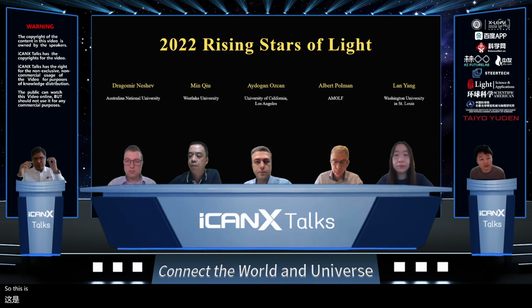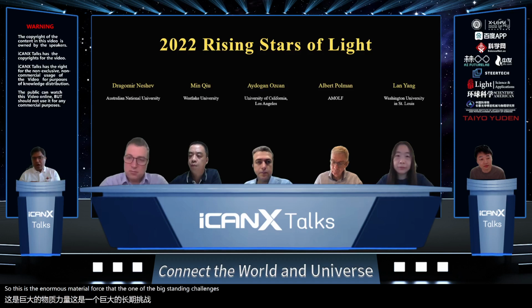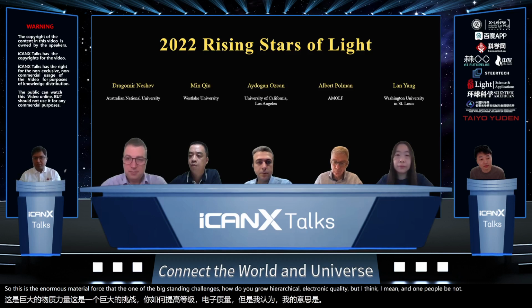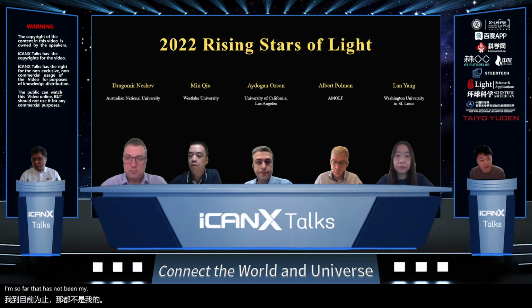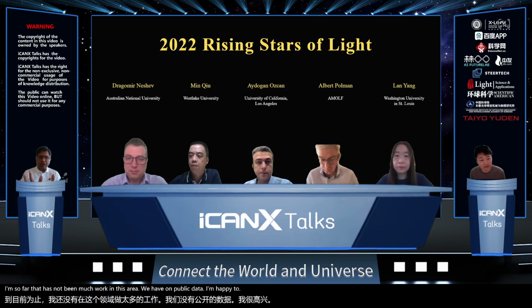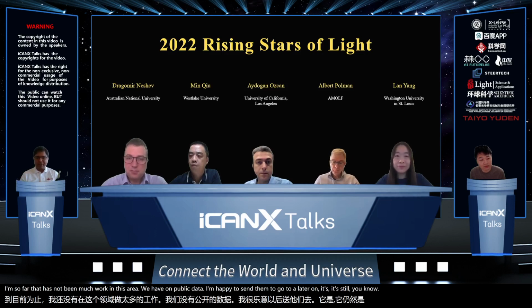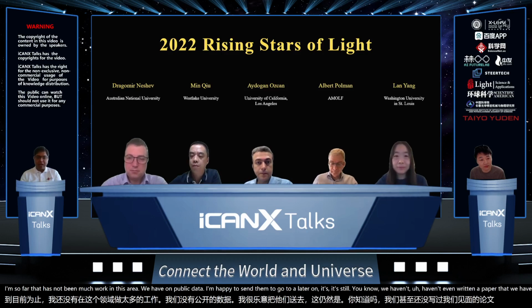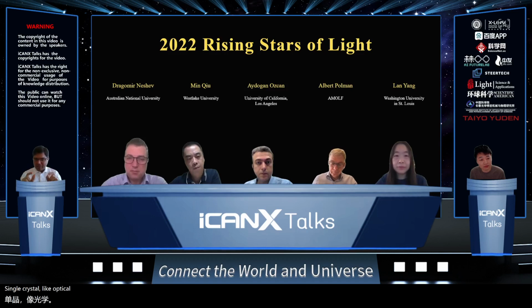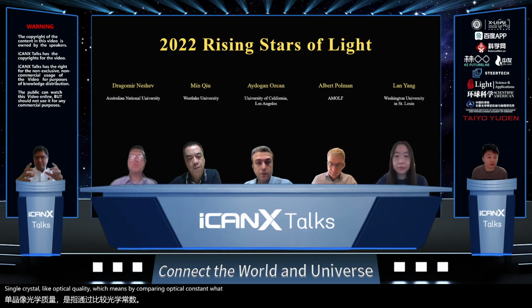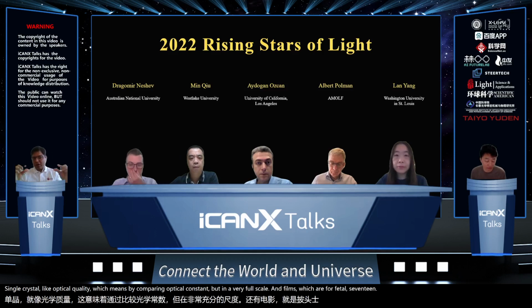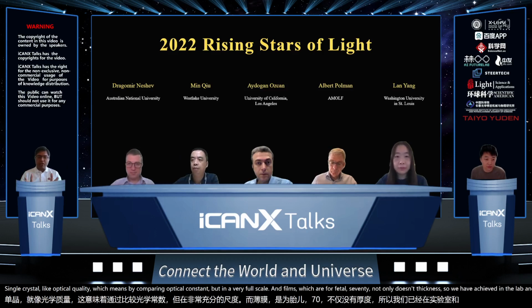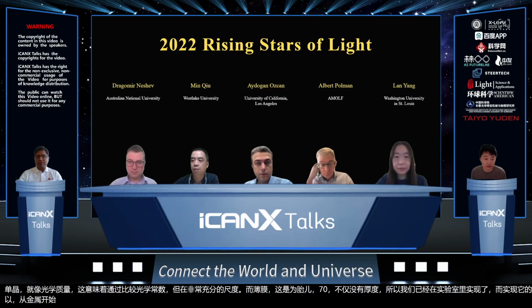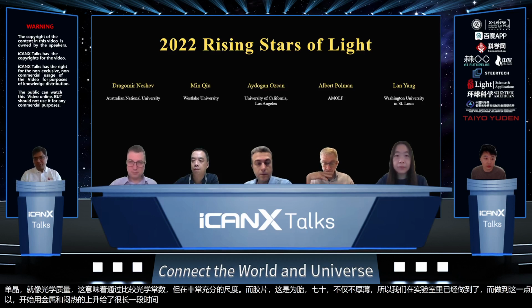So this is, from a materials perspective, one of the big standing challenges. How do you grow high optical and electronic quality, but thick? By thick, I mean 10, 20, 30 nanometer layers. So far, there has not been much work in this area. We have unpublished data. I'm happy to send it to you later on. We haven't even written a paper yet, but we have managed to make single-crystal-like optical quality, by comparing optical constants, in wafer-scale thin films which are 50 to 70 nanometers in thickness. So we have achieved this in the lab. And the way to do it is not by molecular-scale precursors, but by starting with the metal and sulfurizing it over a long period of time on an epitaxial substrate.